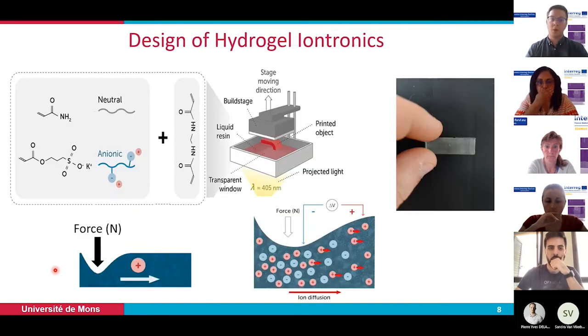So in our study, we use a neutral matrix, which is acrylamide, and we put in a macro ion, which is fixed within this matrix and which has small counter ions. This is really important because by fixing these macro ions in the matrix, you increase the difference of mobility between these macro ions and the counter ions, which are not fixed in the material and can move freely in the material. So you will increase your signal like that. We have printed these materials, so we can see a picture here of our systems.